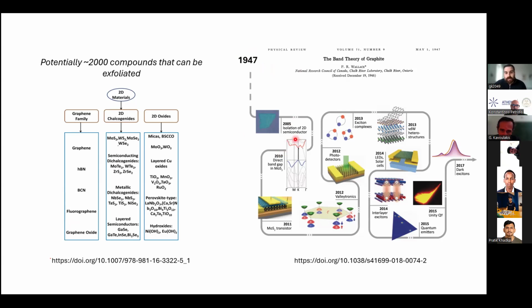And of course, we follow the path through finding two-dimensional semiconductors, building the first 2D transistor, going to the area of valleytronics, where in TMDs you have a very strong spin-orbit interaction and also a broken inversion symmetry. That basically can create, in simple words, a binary system where the role of zeros and ones is played by spin values, spin up and spin down, and you can, in principle, transfer and store a great amount of information in these materials through this property.